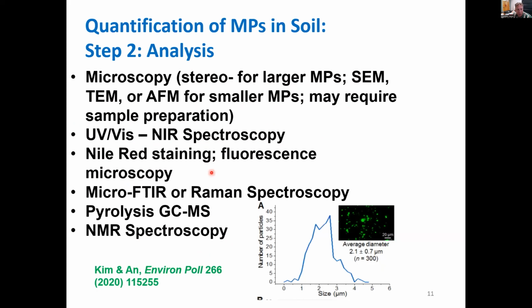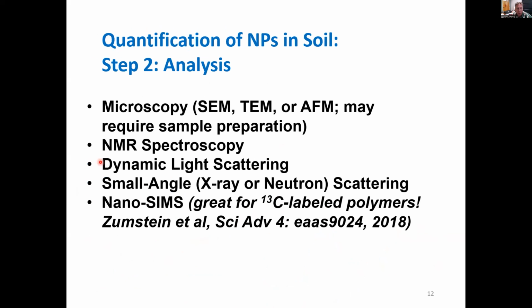Another workhorse is to use fluorescent microscopy using Nile red staining, which is also something that was talked about in the previous presentation. And you can see an example here in the bottom from the literature of that approach. Also, FTIR or Raman spectroscopy as a microscope is also common. We can do GC mass spec with pyrolysis. And then NMR works really well for biodegradable plastics.